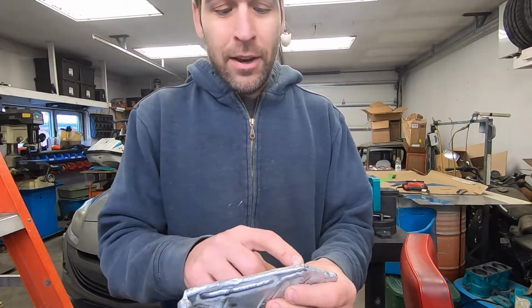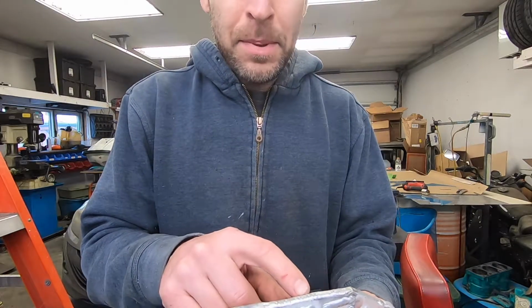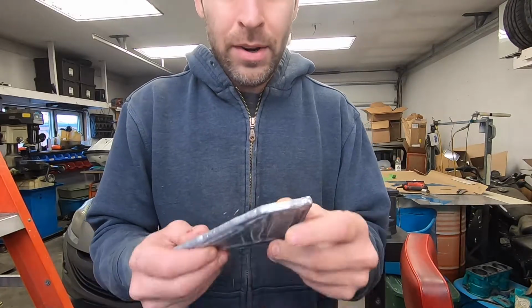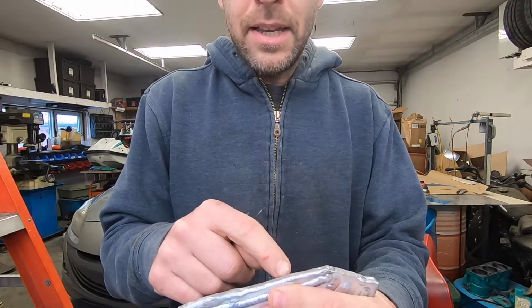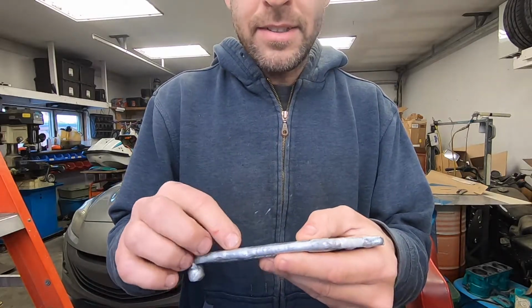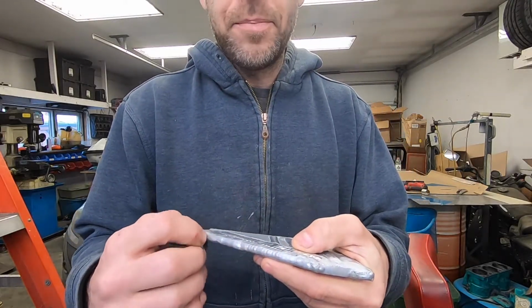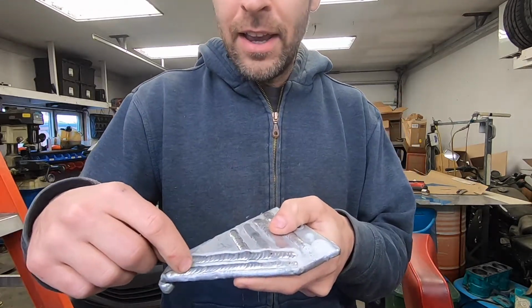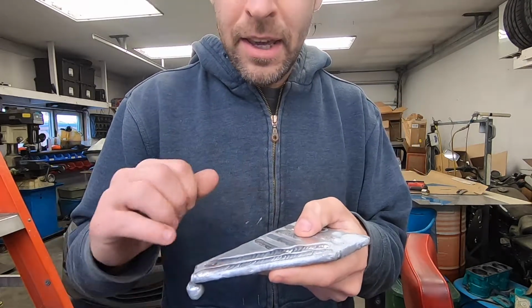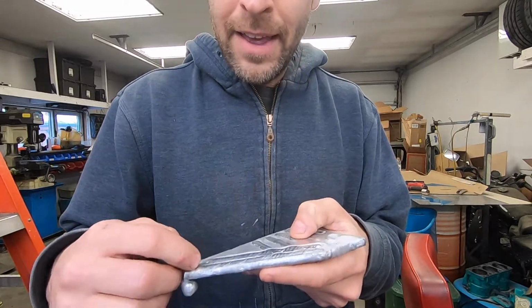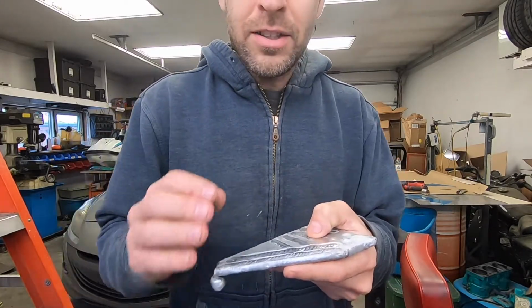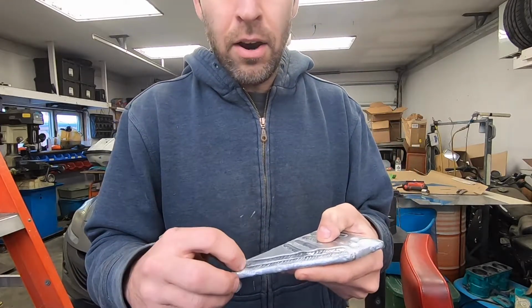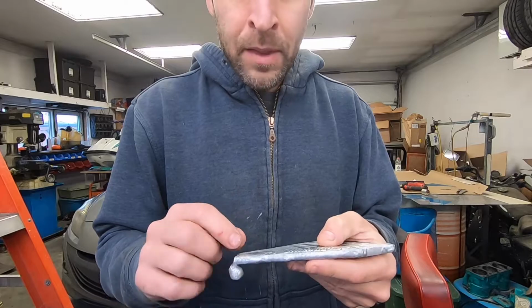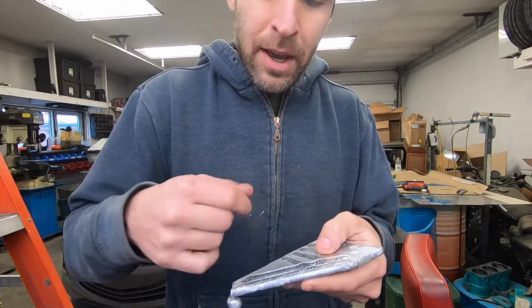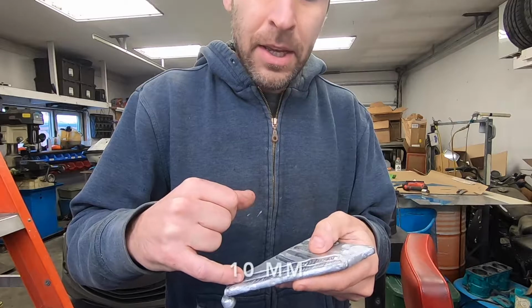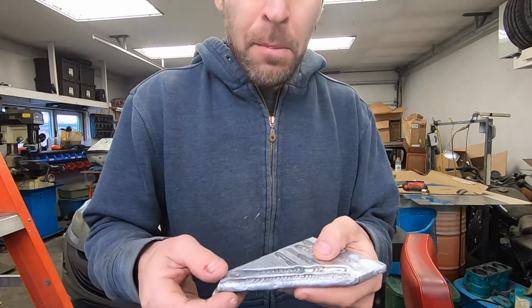A few days earlier, I had actually laid a test bead along the top edge of this 1/4 inch plate. When I laid my test bead along here, it actually deposited some tungsten in that weld. So as I'm welding along here, trying to weld my new bead on, even though it's going fairly well, the arc was jumping off. The tungsten has a lower resistance, and so the current wants to pass that way. So even though I was trying to focus my arc, I was trying to stay about 10 millimeters over from the edge, but I just couldn't do it.